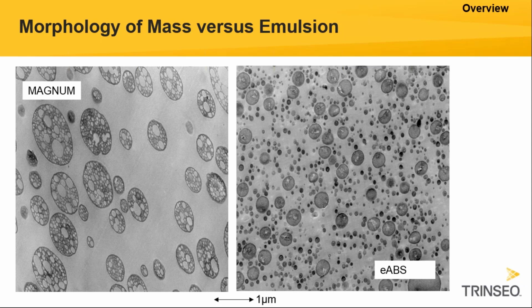Now, if we look more into detail on the left picture, you can see that the rubber particles are fairly large in size and they contain many SAN occlusions. So there is styrene acrylonitrile polymer inside the rubber particles. This is an immediate proof of the very high rubber efficiency of the Magnum polymerization process and makes it less sensitive to rubber degradation.